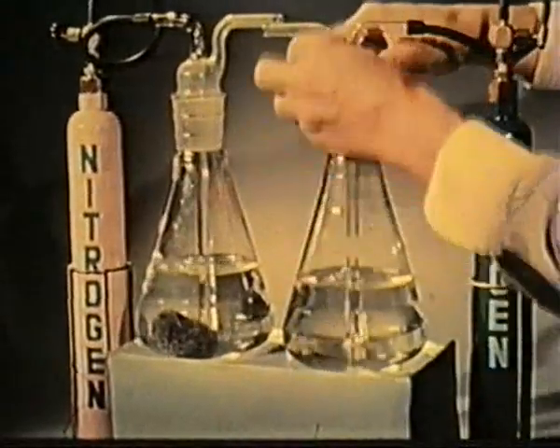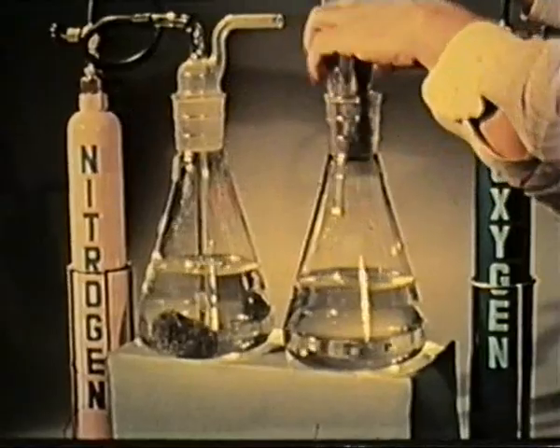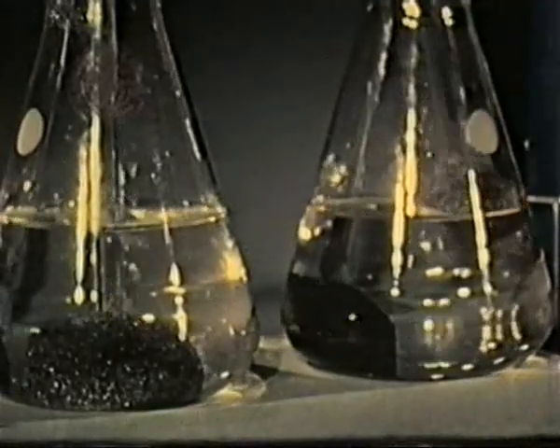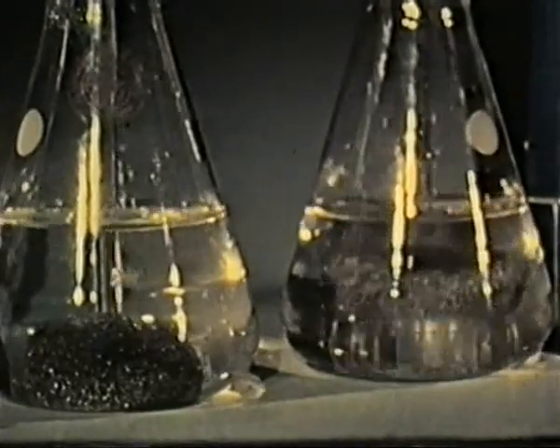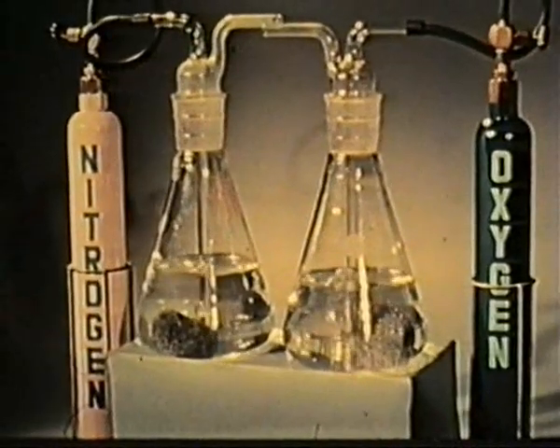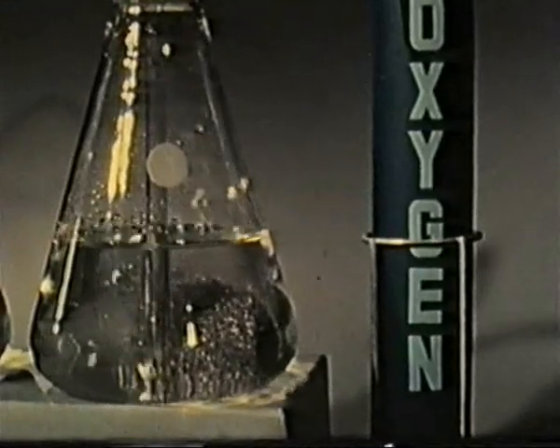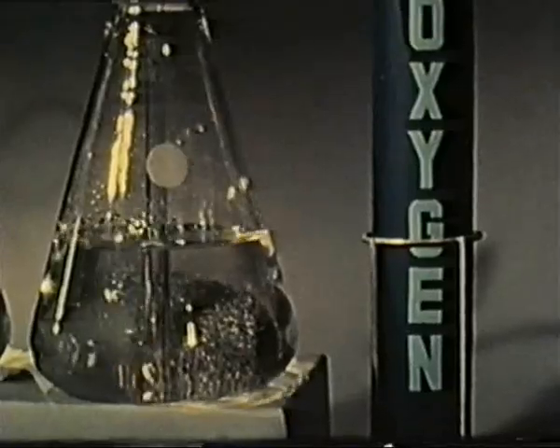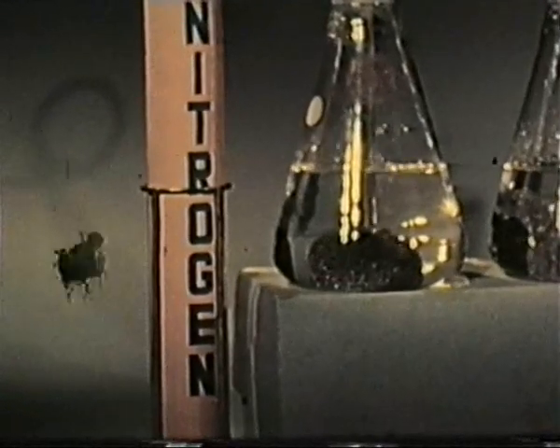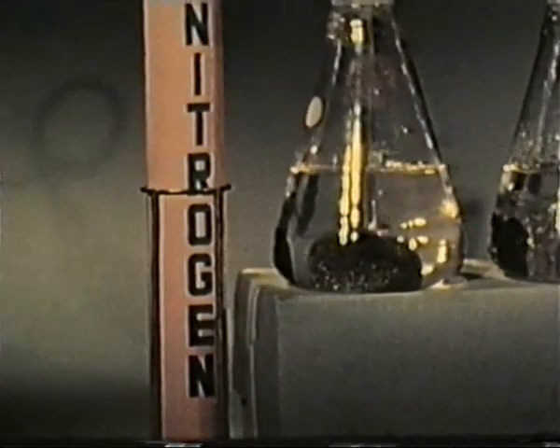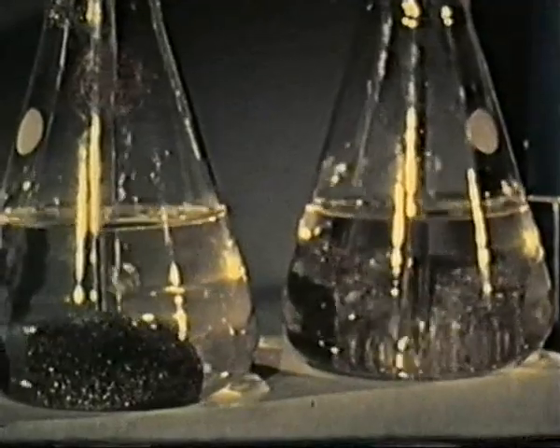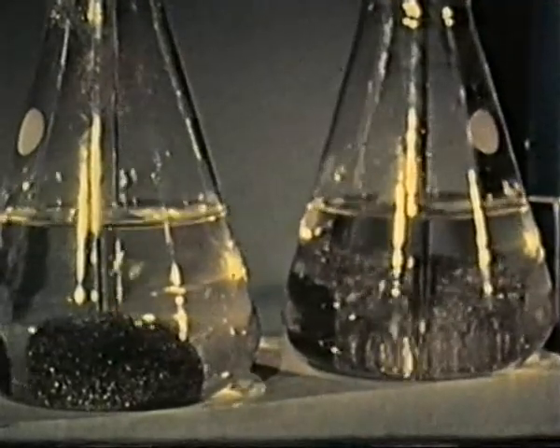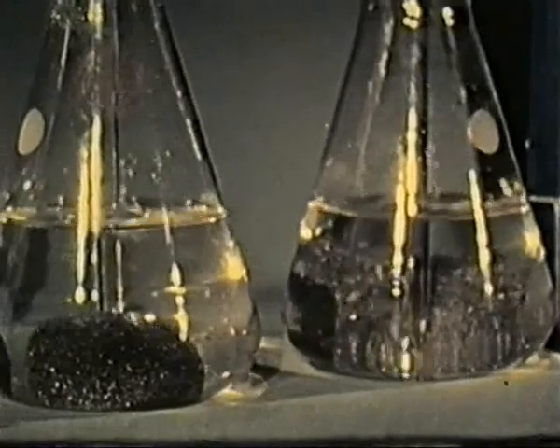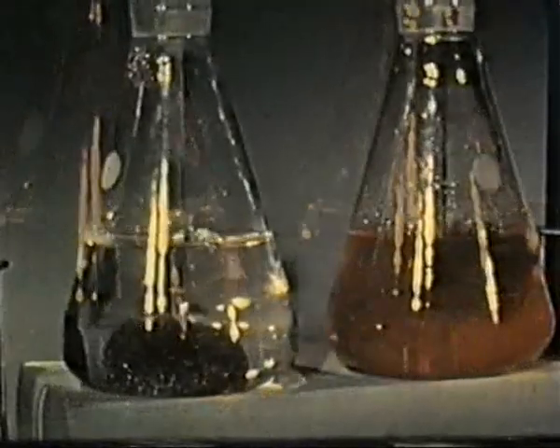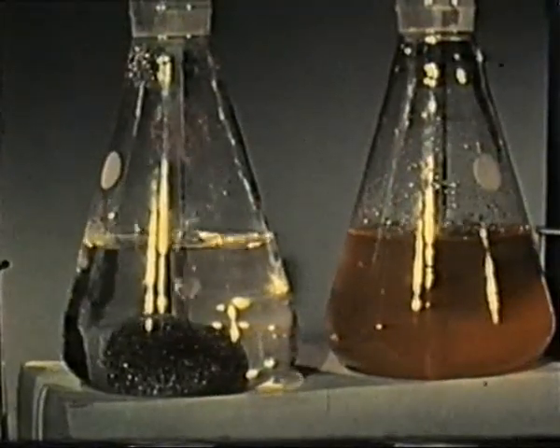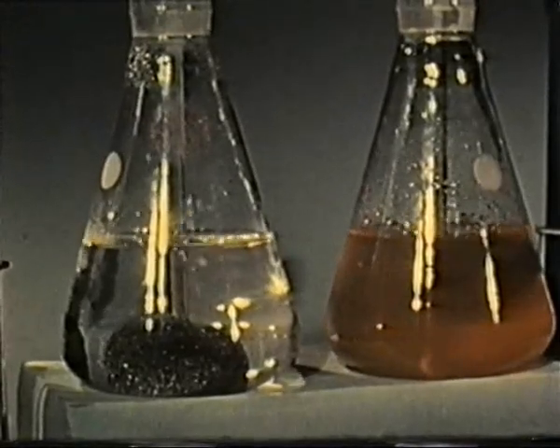The action of oxygen in furthering corrosion can also be demonstrated by placing iron turnings in two flasks filled with water. We'll allow oxygen to bubble through the water in one flask to supply it with oxygen, and we'll saturate the second flask with nitrogen, which drives oxygen out of solution. After they bubble for 2 or 3 hours, we'll find that the iron in the oxygen-free nitrogen solution is as bright as ever. But the iron in the water saturated with oxygen has already begun to rust.